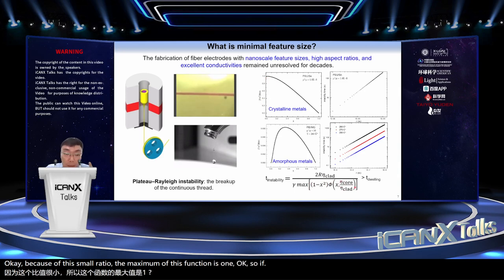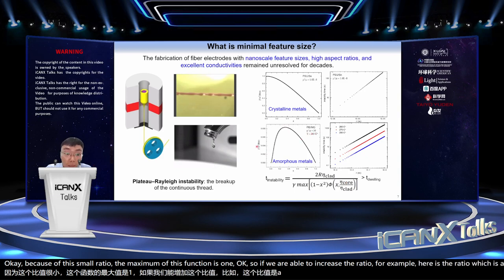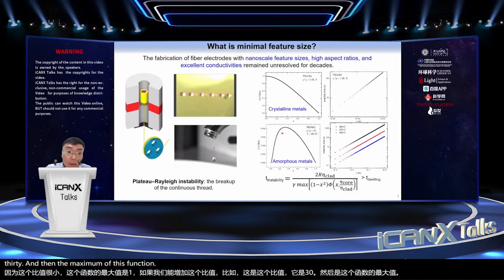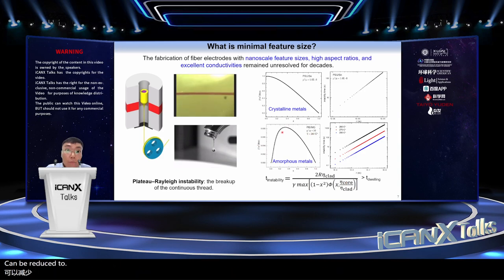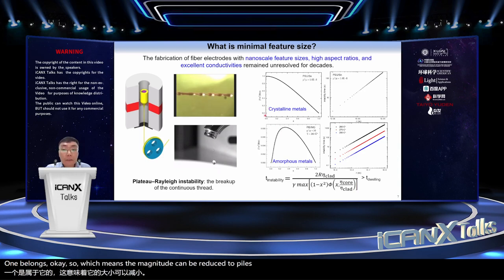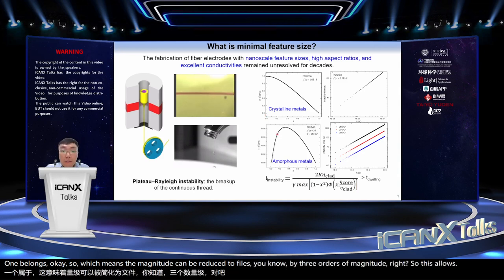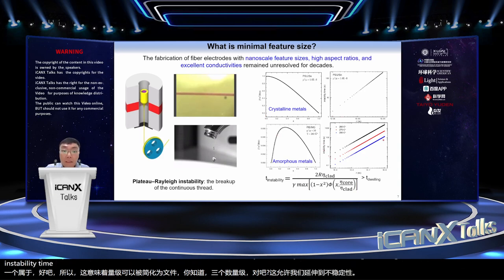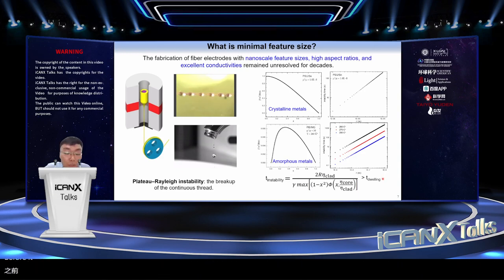So if we are able to increase the ratio, for example, here, the ratio which is 30, then the maximum of this function can be reduced to around 0.001, okay? So which means the magnitude can be reduced by 3 orders of magnitude, right? So this allows us to extend the instability time from 1 second to 1,000 seconds. So we have enough time to process the material before it breaks up into spheres, okay?